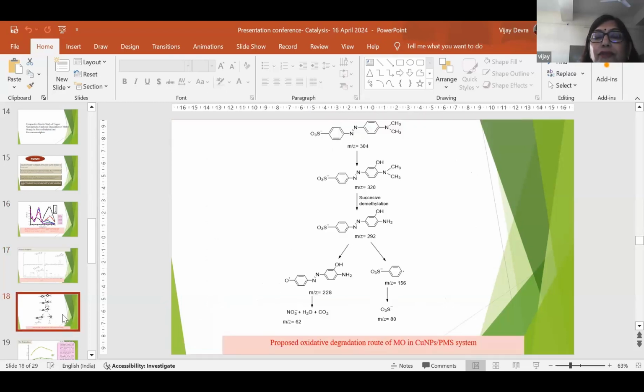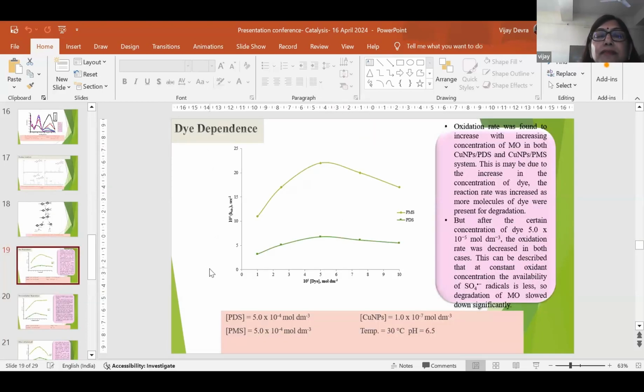And this is the proposed oxidative degradation of methyl orange in the copper nanoparticle peroxomonosulfate system. This clearly indicates that methyl orange degraded in the presence of the copper nanoparticle into harmless products. Now I'm discussing the various kinetic parameters, such as the effect of dye dependence, as we show in both systems, peroxomonosulfate and peroxodisulfate. The rate of degradation of methyl orange initially increases up to a particular concentration of the dye, that is 5 × 10^-5. After that, the rate of degradation decreases as we increase the concentration of the dye at the fixed concentration of the other reactants and conditions.